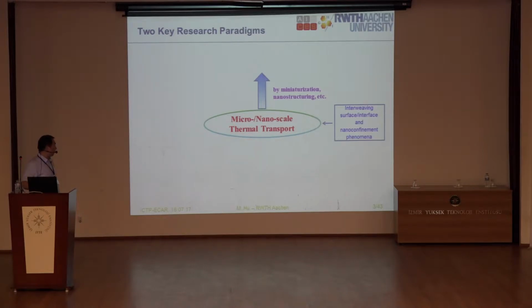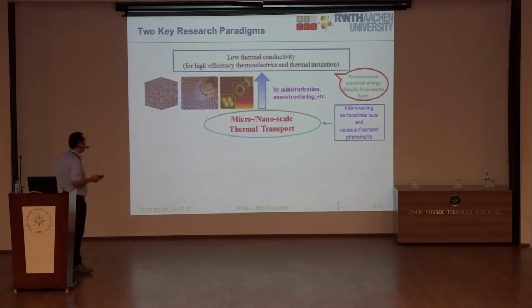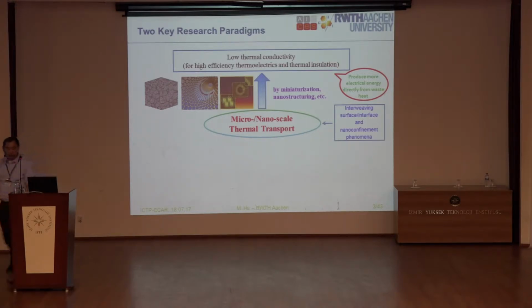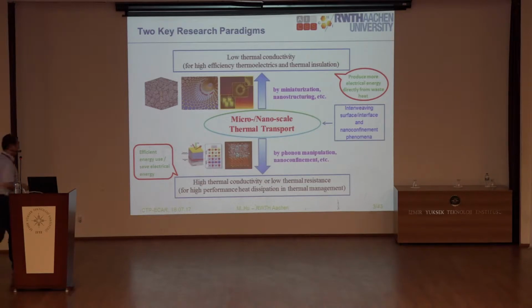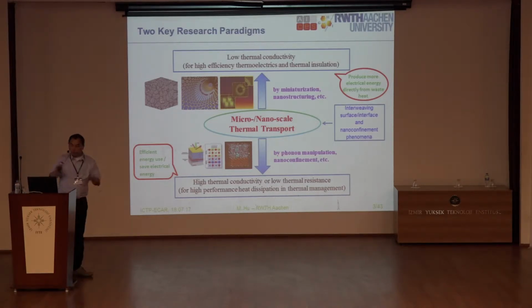On the one hand, by miniaturization, if you make the structure smaller and smaller, nanostructuring can make heat dissipation more difficult, so that a very low thermal conductivity can be realized, which is of course beneficial for high-efficiency thermoelectrics or thermal insulation. In this case, you don't want heat to flow in the structure. But sometimes we do want heat to go through the material very quickly. This is associated with high thermal conductivity for some materials or low thermal resistance across the interface, which can be beneficial for high-performance heat dissipation in thermal management. Of course, you can also manipulate phonons and take advantage of some phonon confinement effects.